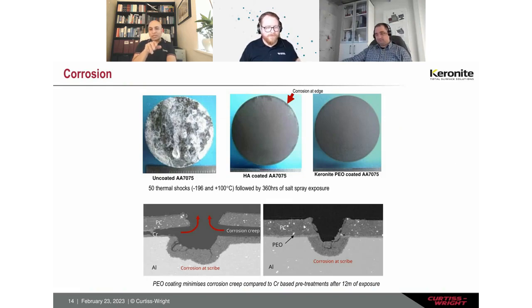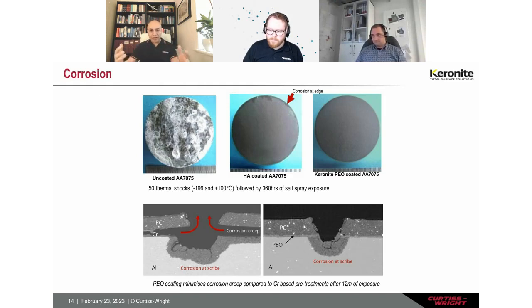There we go. So what is happening there? Just to respond to Sankara's question, you have got the PEO layer on the aluminum substrate, which is an atomically bonded thin layer, it's got a very good bond. But then you have got lots of pore architecture in the PEO. So what this PEO is doing here is acting as a bond layer for the powder coat or paint or subsequent layer. So it is extremely well bonded to the PEO layer. So you have got the extremely well bonded PEO to the substrate and extremely well bonded top layer to the PEO. And because PEO is electrochemically an inert layer, you don't have the galvanic interactions between the alumina and the aluminum substrate.